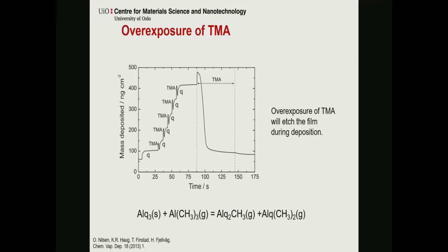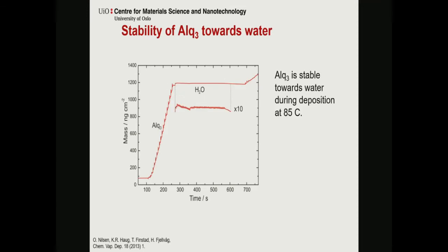So by overpulsing the metal again, you can etch the film. It happens that we found a work from the 60s that actually shows another stoichiometry between aluminium and the 8-hydroxyquinoline, which is more volatile. So in this case, when you change the composition during growth, you lose film. And this may also cohere to what we saw from some of the strange growth rates later on and overpulsing of the metals.